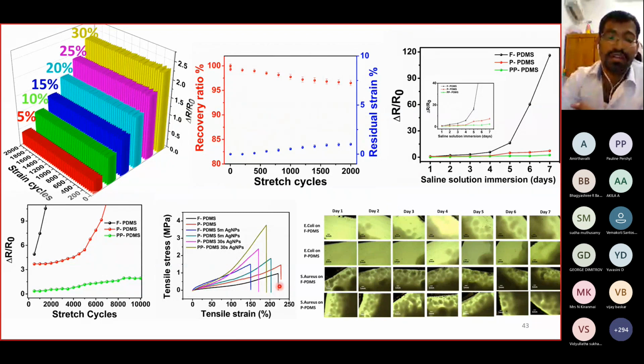Here we can see they have very good mechanical strength compared to flat structures. Flat structures are soft and don't have higher toughness, whereas patterned PDMS electrodes have very good toughness. So it can be good for wearable applications, and it will have very good stability. In terms of antibacterial effects, they are also quite good, because we have silver nanoparticles which provide these kinds of properties.